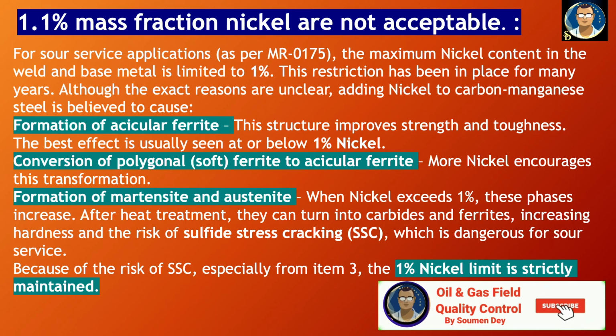The restriction has been in place for many years. Although exact reasons are unclear, adding nickel to carbon manganese steel is believed to cause the following issues. Formation of acicular ferrite. The structure improves strength and toughness. The best effect is usually seen at or below 1% nickel. The conversion of polygonal ferrite to acicular ferrite, more nickel encourages this transformation. Formation of martensite and austenite. When nickel exceeds 1%, these phases increase. After heat treatment, they can turn into carbide and ferrites. So it will increase the hardness and risk of sulfide stress cracking, which is dangerous for sour service.